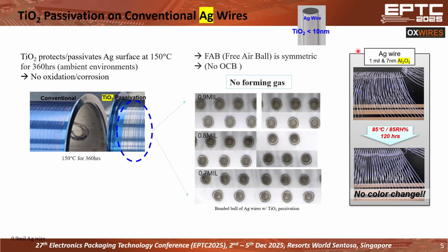And TiO2 is not the only passivation we can apply. On your right hand side, you can see the Al2O3 was applied on a 1 mil diameter of the silver wire after exposing the wire to 85 degrees C, 85% relative humidity for many hours. No color change occurred. It indicates that both TiO2 passivation and Al2O3 passivation protect the surfaces of the silver wire from oxidation and corrosion.